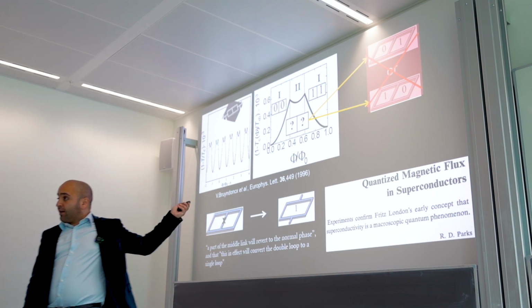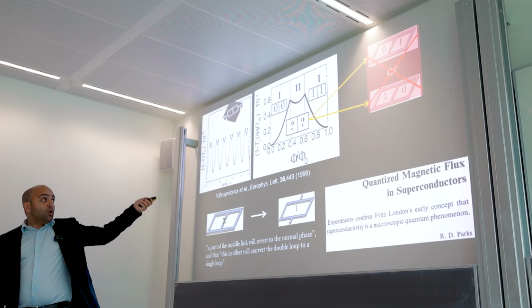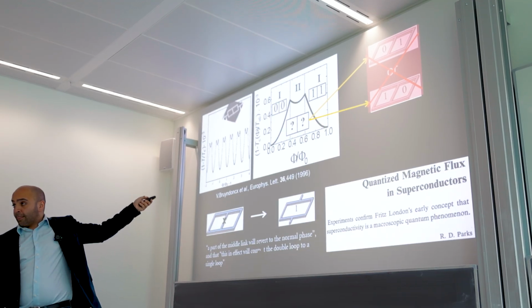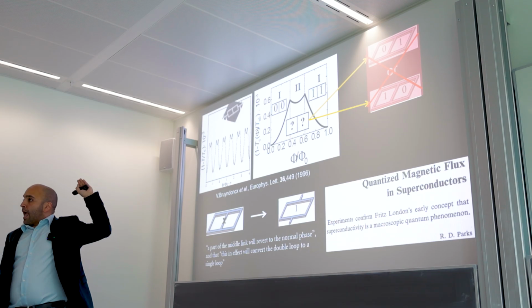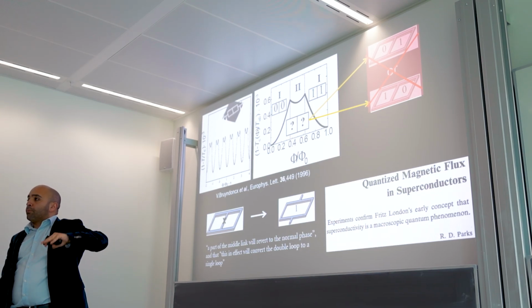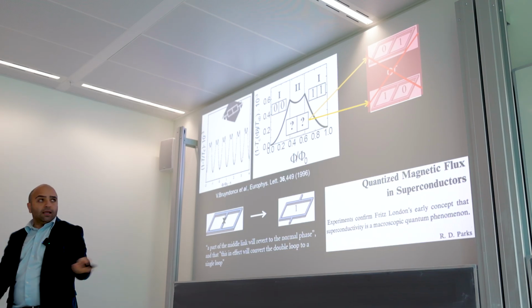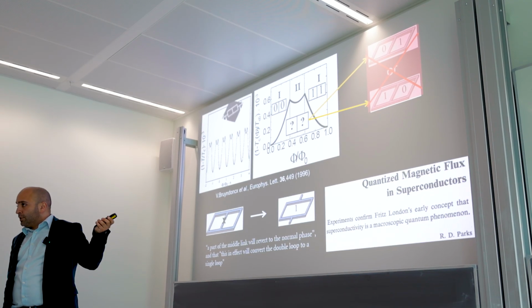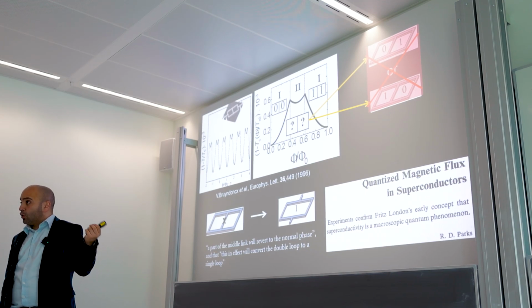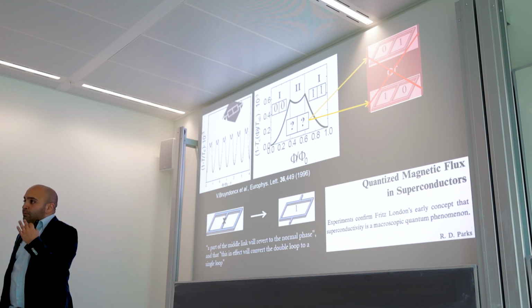So in this case, even if you go far below the transition, this is the crazy thing, even if you cool down your system in this region, apply this field and cool down and you go to 1% of your TC. So when you're in the fully superconducting state, this part would refuse to be superconducting. It would actually remain normal regardless of how low you go in temperature. But here's where it gets even more crazy.